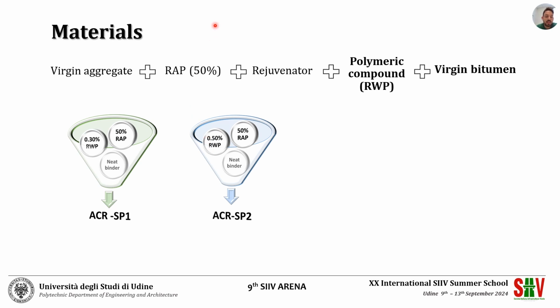The asphalt mixtures investigated in the study were produced by combining different base materials. Two sets of asphalt mixtures modified with waste plastics were prepared using two different levels of polymeric compound, 0.3% ACR-SP1 and 0.5% ACR-SP2 by weight of the black mixtures.